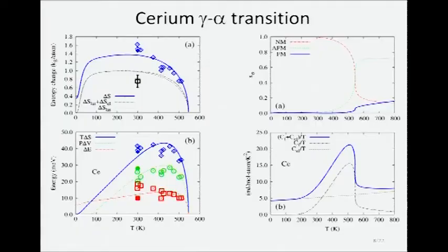Here, talking about the distribution among different states. We specifically show the configurational magnetic heat capacity. This looks amazing, because for other systems I didn't get this. Especially for this one, talking about entropy change between two phases - this measures the lattice contribution, the total entropy contribution. There you see our calculation.